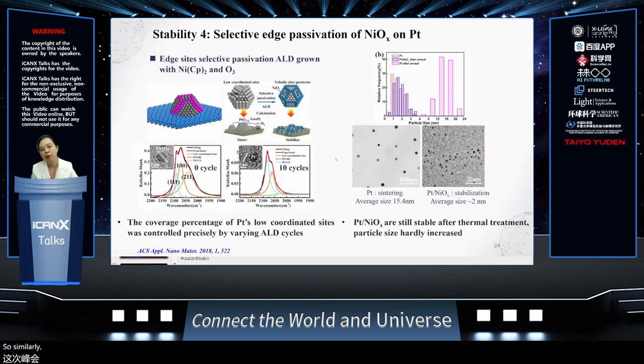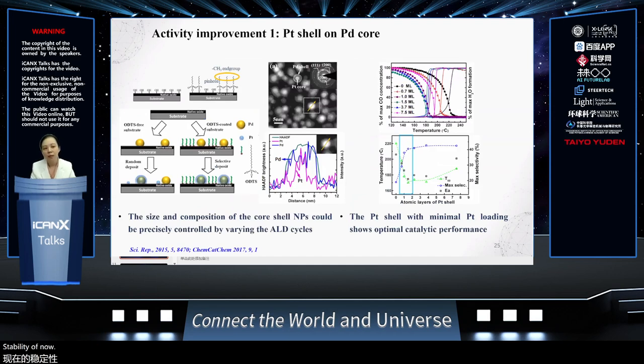Similarly, if we choose another type of metal oxide with a different co-reactant, we'll be able to selectively coat this kind of edges. And once you coat the edges, you form these nice interfaces, and you also stabilize the metal particles. So all of these four examples show how selective ALD helps to improve the stability of the nanoparticles. Next, I will use a few examples to show you how we can do the structural changes to obtain this kind of enhanced activities.